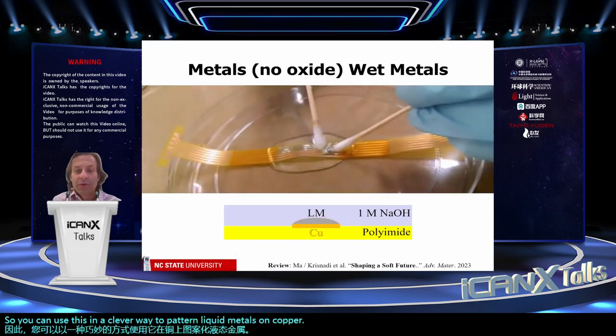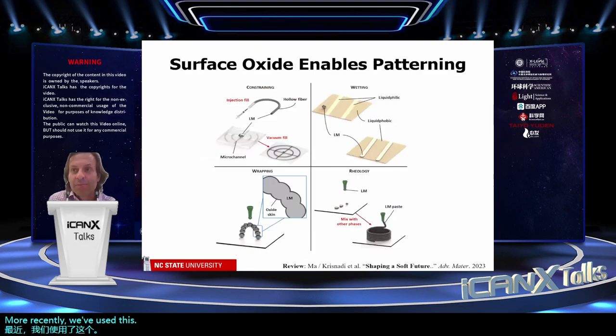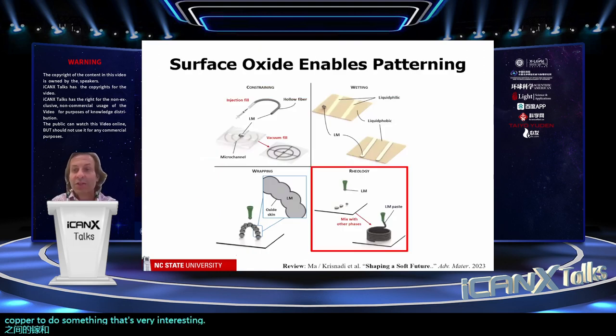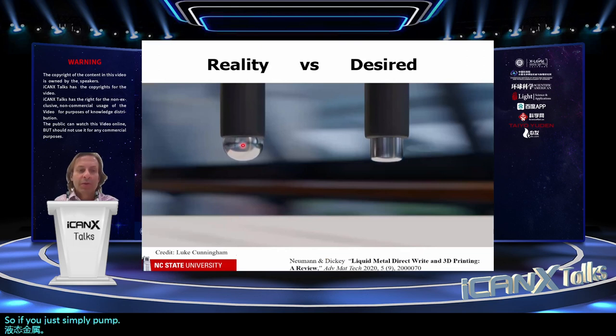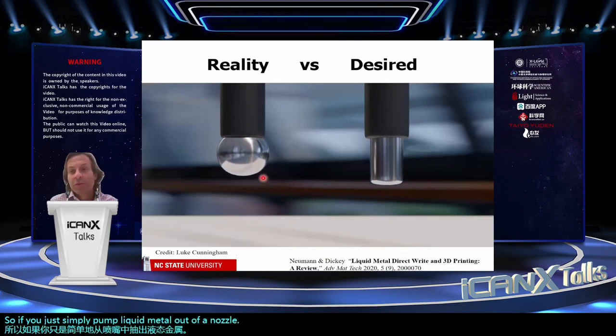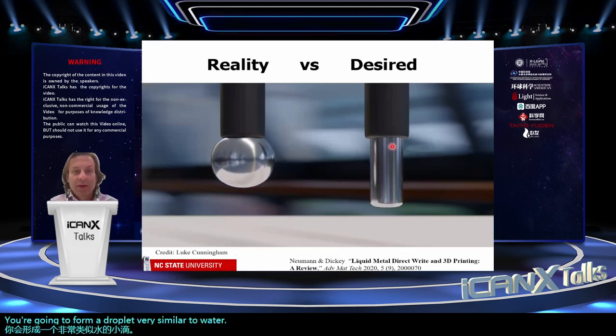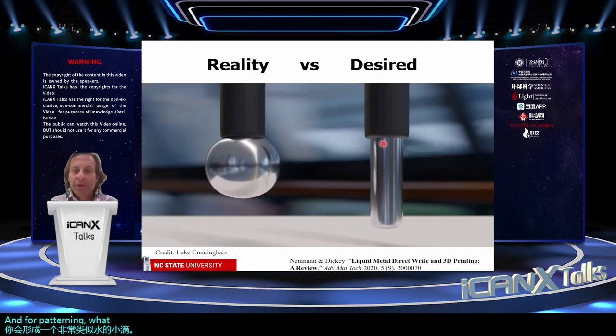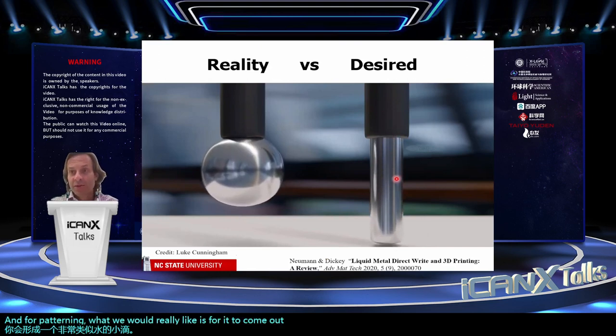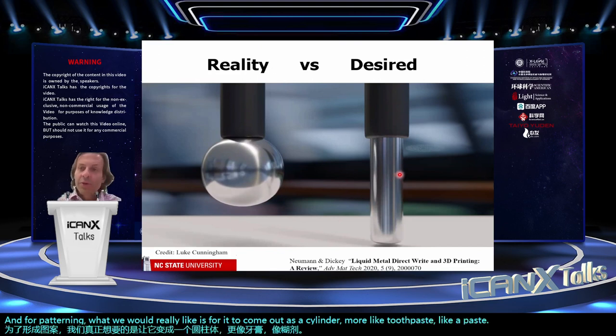More recently, we've used this wetting between gallium and copper to do something that's very interesting, and that is adjust the rheology of the liquid metal. So if you just simply pump liquid metal out of a nozzle, you're going to form a droplet very similar to water. And for patterning, what we would really like is for it to come out as a cylinder, more like toothpaste, like a paste. So how do we do this?